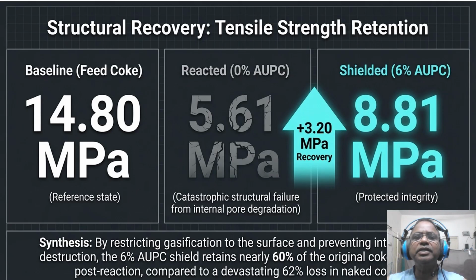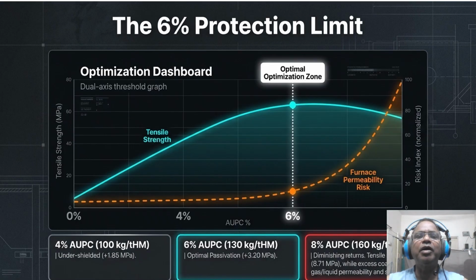So by restricting gasification to the surface, we are retaining nearly 60% of the original 14.8 MPa coke strength. Without that shield, you are looking at a devastating 62% loss in integrity. That is the difference between a stable hearth and a catastrophic structural failure. But you cannot just keep piling on coal. There is a hard physical limit, and this slide talks about those limits.